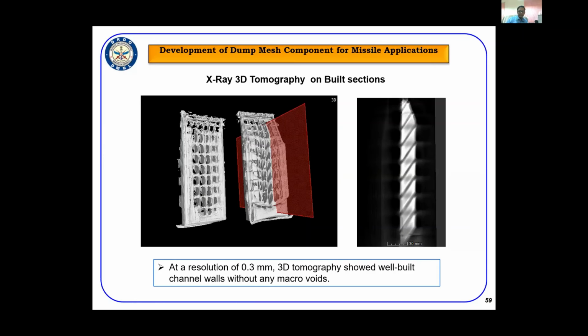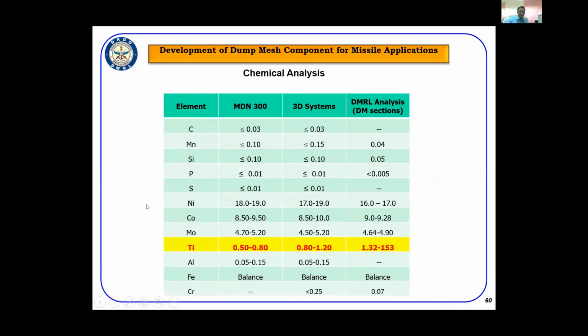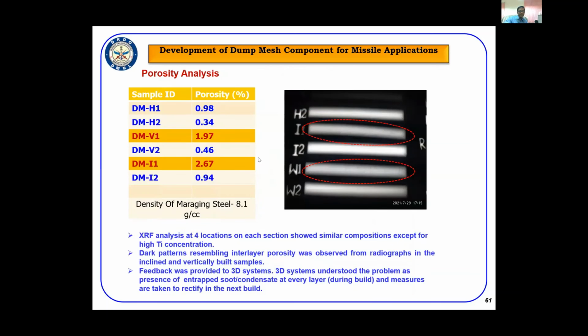And again, this component also has been subjected to 3D tomography to understand, layer-wise, what sort of features are there in different layers. And we have seen that at the resolution of 0.3, the component has been very nicely built without any voids or porous structures. And we again went ahead with the chemical analysis, which is matching except for the titanium, and otherwise it's matching with the standard specifications and also the input feedstock material. And when we went ahead with the porosity analysis of the specimens which were built along with the component, carried out at 4 locations, they showed a similar composition except for a high titanium composition.